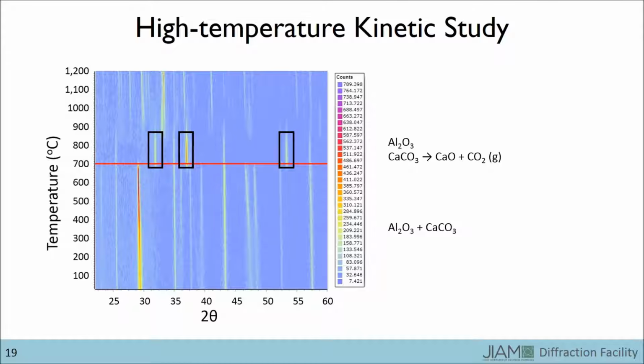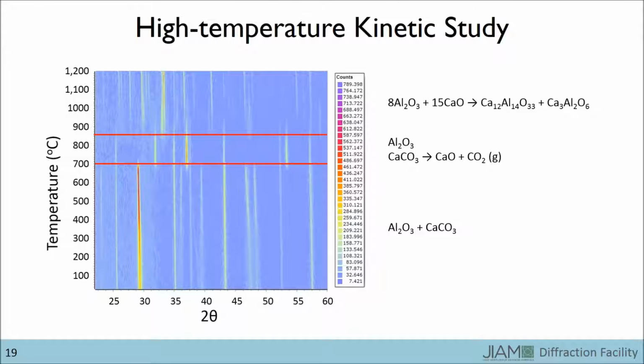As the temperature continued to rise, the user saw another transition around 850 degrees Celsius. This time, the aluminum oxide did react with calcium oxide to form both compounds shown here. With this one experiment, the user was able to determine the reactions and reaction temperatures for every step of the material synthesis.